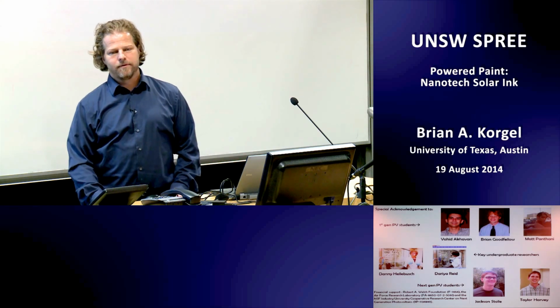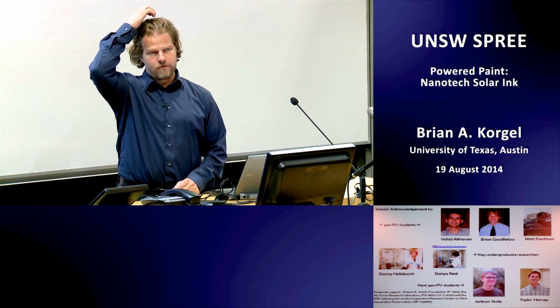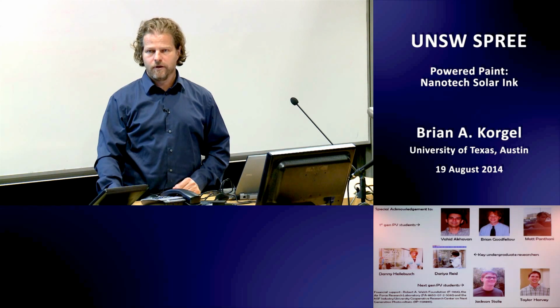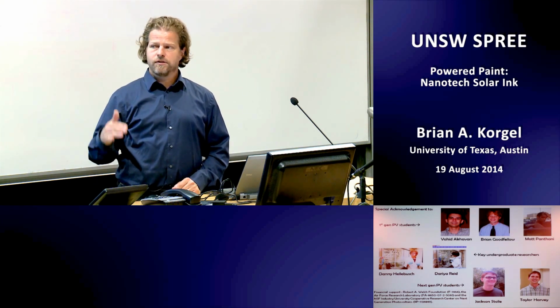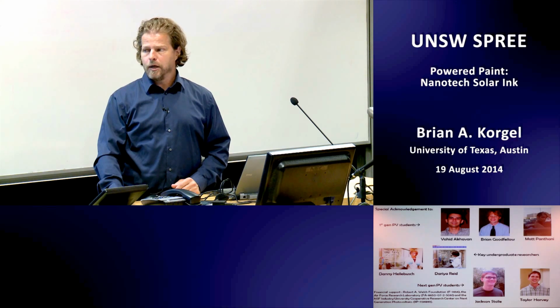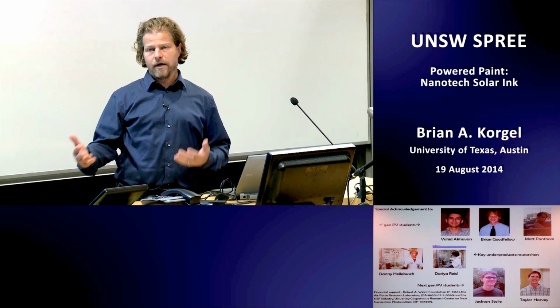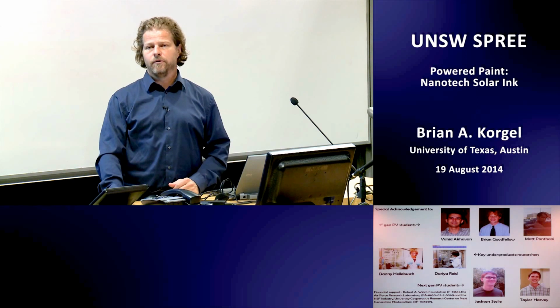So not only do you have to heat to 550 C, you have to do it with the selenium vapor. And so one of my students just spent 2 months in Singapore, where they have a 2-zone furnace for selenization, and so they can control the temperature quite a bit more closely than we can at our facility in Texas, including pretty close control over vapor pressure of selenium. And just small changes in selenium vapor pressure give pretty dramatic changes in terms of selenization and morphology. People are pretty clever, and you can control that to a pretty good extent on manufacturing lines, but still, in the end, that control and the yield of devices is what's really limiting CIGS from becoming commercially viable in the way that cad telluride is.